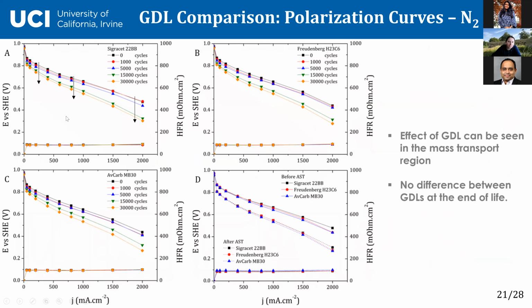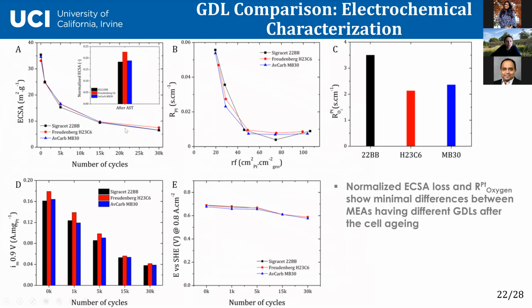We did beginning of life and end of life evaluation. This plot shows it very well. Performance at the beginning of life and the end of life, pretty much it doesn't depend on the GDLs. And this is very interesting because there are so many studies that look into the effect of GDLs, and we show no effect, pretty much a negative result. Platinum will degrade the same way whether you have a GDL with a porous microporous layer or not. You can see electrochemical surface area is reduced the same way for all three GDLs. Oxygen transport resistance is the same. You can see the mass activity is very similar. So we didn't find anything interesting.